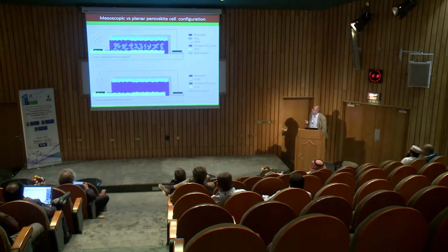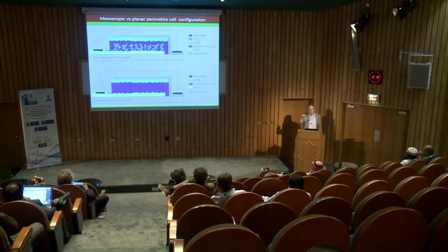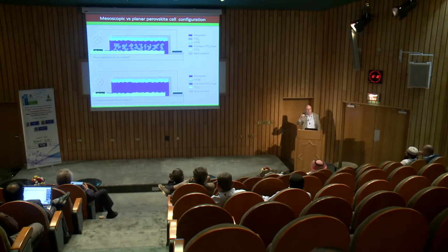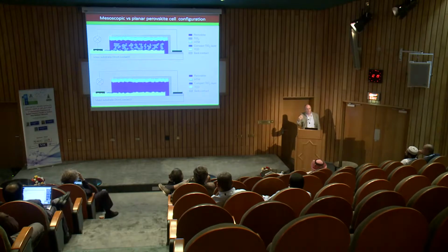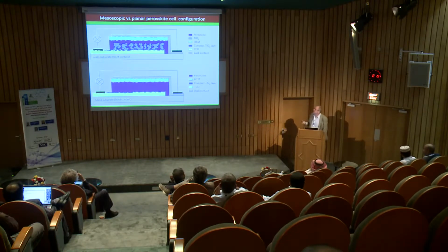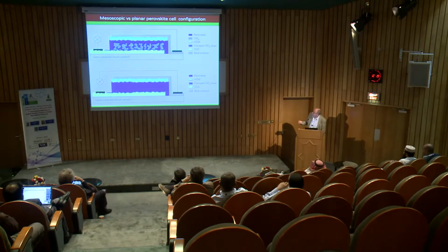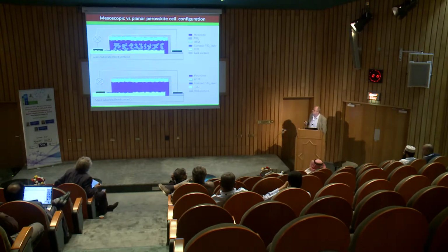I'm at the end. As you saw from the picture, we had a very thin layer of the mesoscopic TiO2, which is useful because we can inject electrons from perovskite to TiO2 like a dye-sensitized cell. On the other hand, most of the perovskite in the film is in a compact layer, so we can ask, can we simply make a planar perovskite layer and then use a contact, FTO with some blocking layer, so we accept electrons but block the holes? TiO2 is the obvious choice, of course. Have a compact layer of perovskite without any nanoparticles, and then the hole conductor and the contact. This is a normal thin film solar cell like CIGS or cadmium telluride and so on.